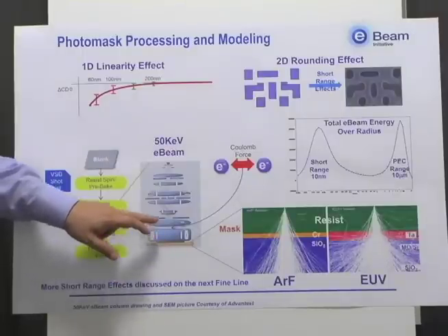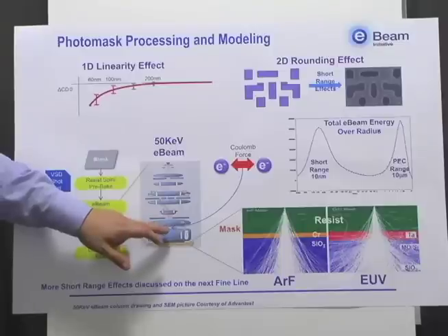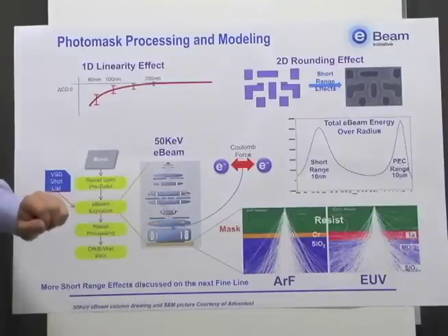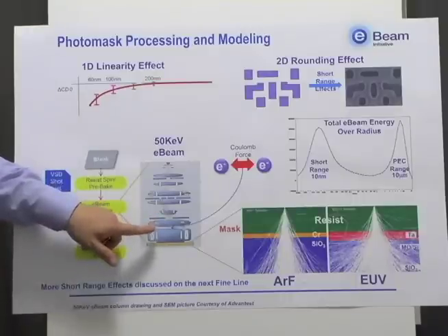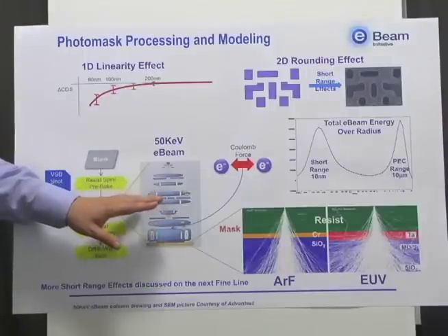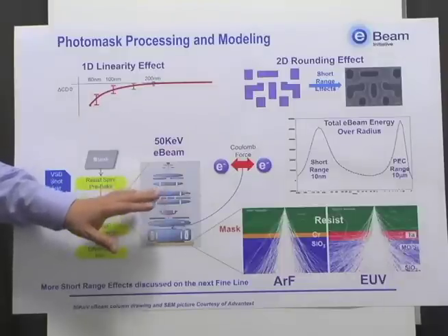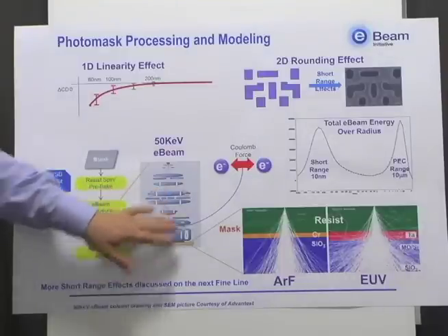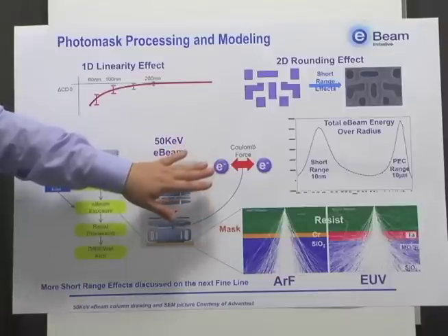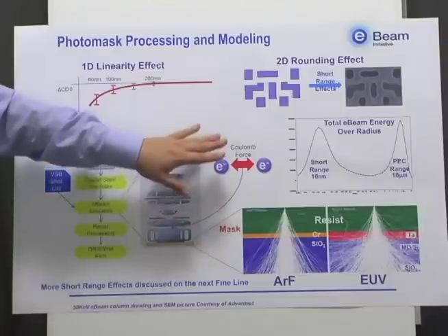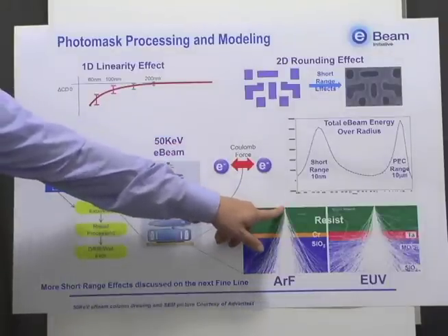Now, in particular, some of this projection process involves a focus, but due to an electron-electron interaction, this focus is going to be of non-zero size and results in a beam blur, which is typically called a Coulomb blur. Mathematically, what happens is this ends up blurring the edges of a VSB shot even before it hits the resist, and the magnitude of such a blur is on the order of 10 nanometers. That blurred shot then impacts the top of a resist material.